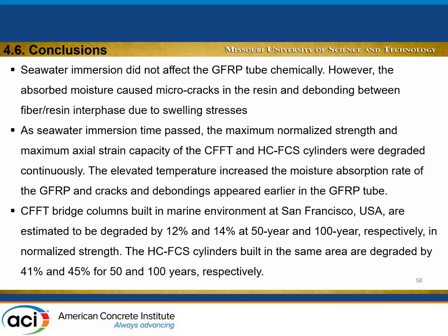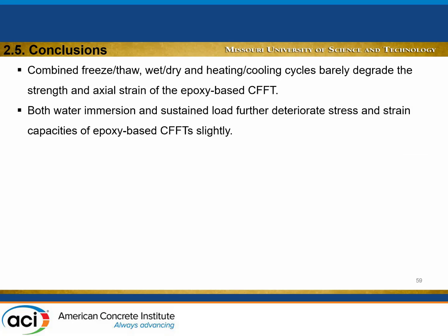So with this, I reach the conclusion of my talk. The most severe condition was the salt solution at high temperature and long duration exposure. UV didn't really do much to the specimens, and generally, as you would expect, epoxy performed much better than polyester. However, when it comes to cost, epoxy is about double the cost of polyester, so you need to do your math and see which one is better for your project. Thank you very much for your attention.